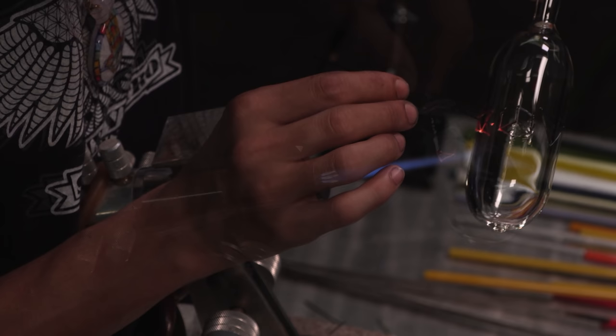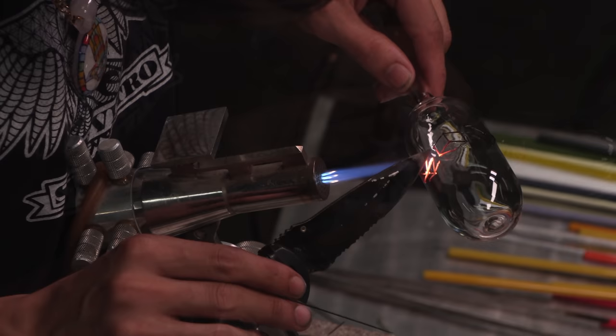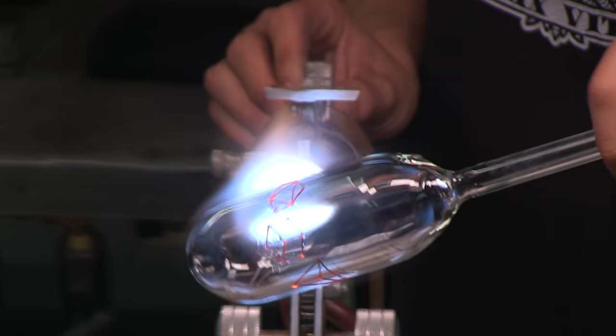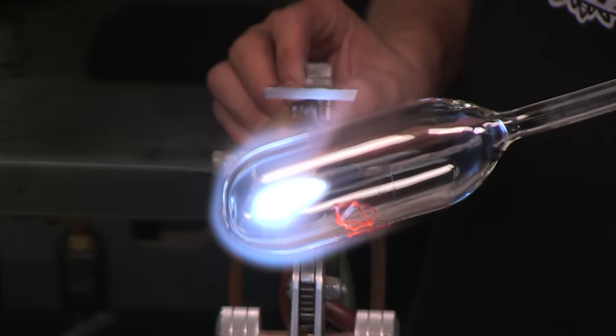And if you do get those lines too hot, you can bleed them out. They'll get too hot and actually melt down to the surface, and they won't be that dark anymore. And that can be a real problem. So a big thing you're trying to do is not get it too hot, because those lines are what's going to dictate how your image looks. They really are the biggest part of what makes your image look like your image. That's what gives it the crisp look, or those crispy little lines.